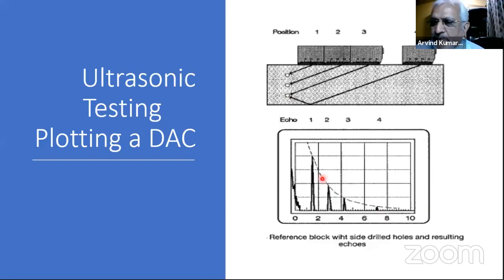So that is why I prepare a distance amplitude correction curve. It is a correction, like I correct this amplitude to this, for whatever distance I travel within the material, to say that this height and this height, from the defect point of view, are the same.